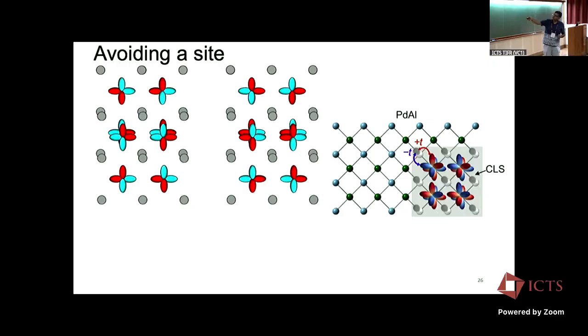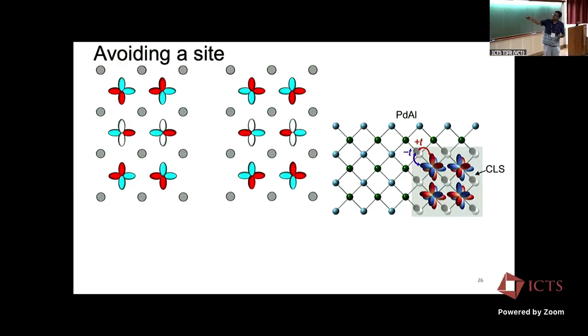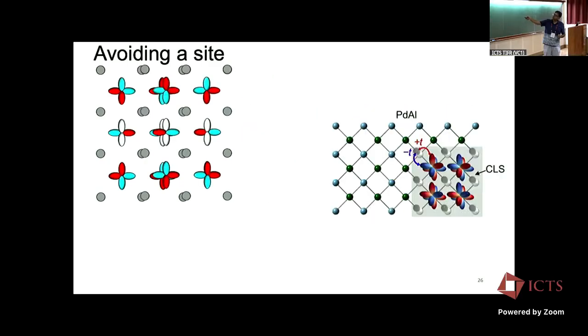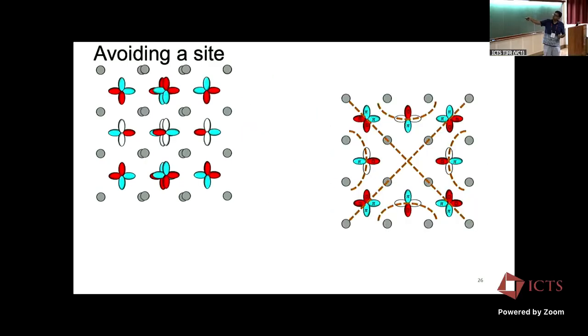then I get, the white here means 0, and then I superpose these 2 together, I add them together, and eventually I get a complete cancellation on this particular site. So it's very much like the Kagome lattice, except it's different since it's a decorated checkerboard. And what you'll get is an eigenstate of the Hamiltonian that lives around a defect. And this eigenstate has a very particular symmetry. You can see that it has a D-wave-like symmetry. It has nodes along these 2 directions and maxima along the other direction.